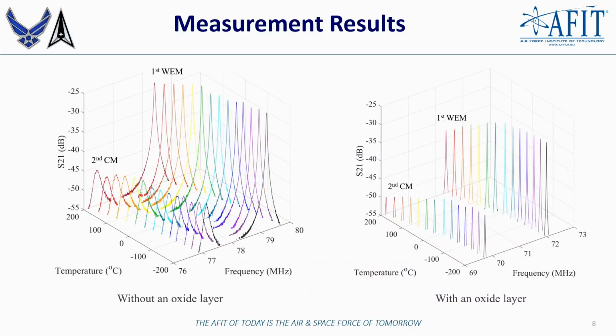So here we present the 2-port S parameter measurement results for our resonators over a wide temperature range, from -200 up to 200 degrees Celsius. On the left here, we have the resonator without an oxide layer, and on the right, we have the resonator with an oxide layer. As temperature changes, we observe frequency shift for both the second contour mode and the first width extensional mode. Despite the oxide layer lowering the overall resonant frequency due to reduced effective acoustic velocity, the temperature coefficient of frequency, or the TCF, is nearly identical for both resonators. The presence of the oxide layer does not significantly alter the TCF, as evidenced by the consistent frequency shift in both cases.